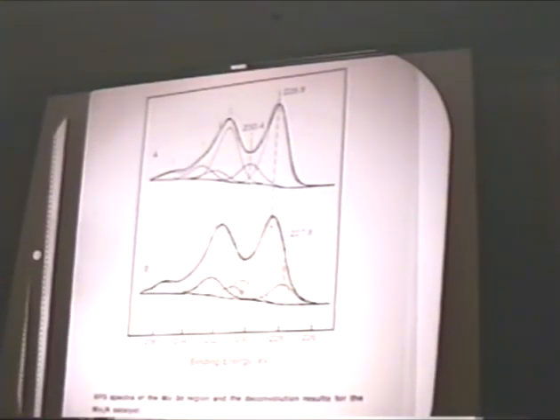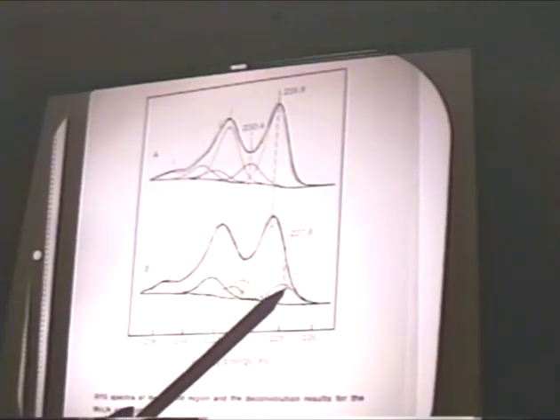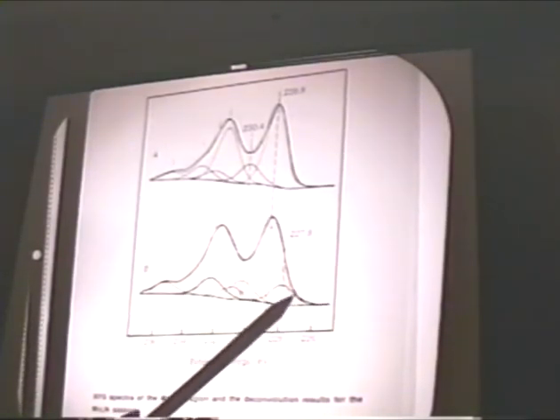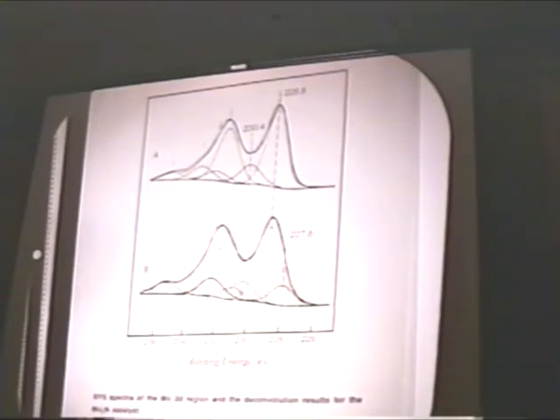This is the catalyst which has gone through hydrodenitrogenation reaction without sulfur compounds. Now, in addition to the 3d convolution peaks that we obtain, now there's another peak appearing here at around 227.8 eV. And from the literature, we have found some studies which report that molybdenum carbide has a signal around this binding energy level.